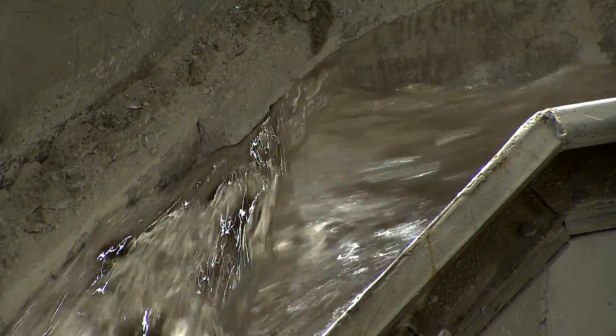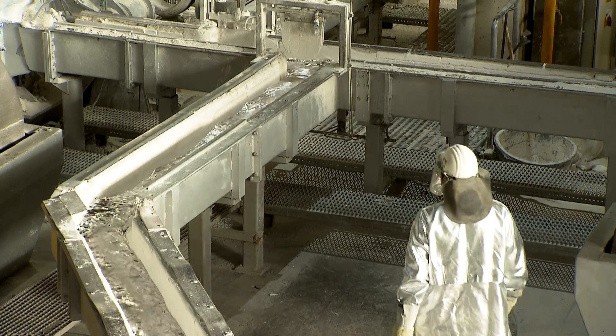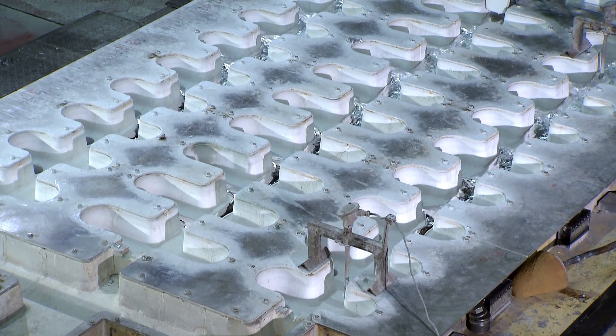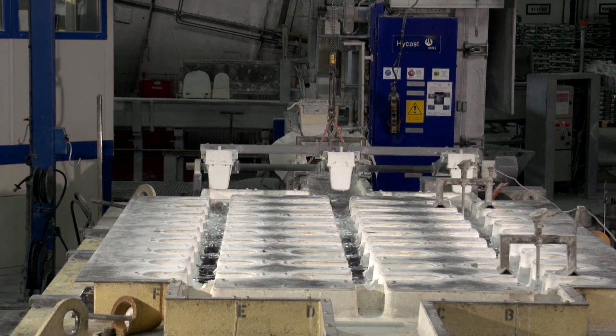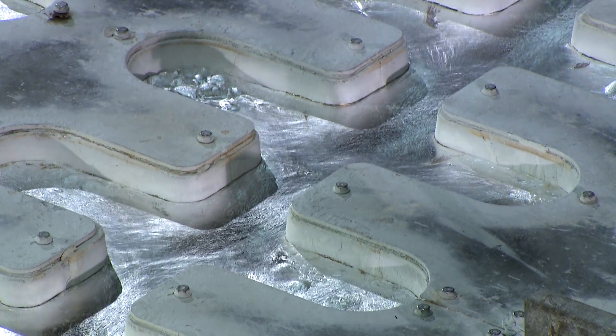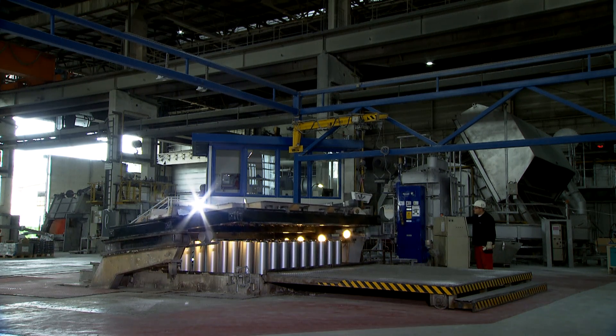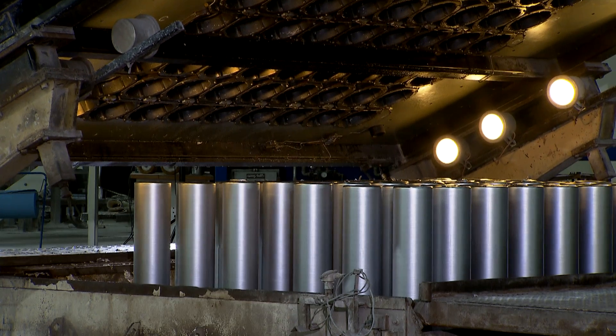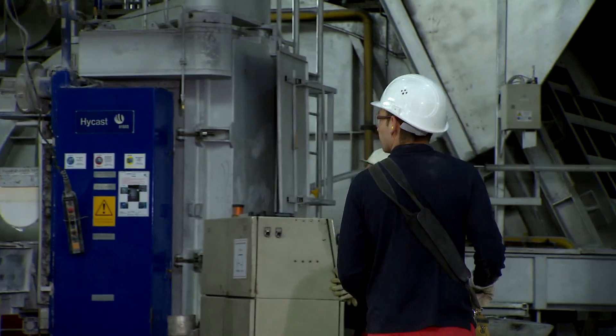The recycling material is melted down at the plant in Rakwitz. With the help of a special procedure, aluminum billets measuring some 25 centimeters are produced under a casting table. The billets are lowered into a hopper, and after a cooling phase, the so-called extrusion billets are ready-made from the recycled aluminum.